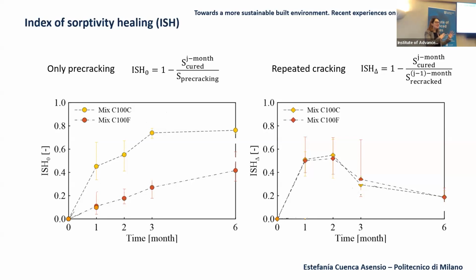This is in terms of sealing only at the surface, but what happens in the crack depth, regarding the inner part of the crack? Is it repaired or not? The structure is the same. On the left, we are analyzing only pre-cracking, not the recracking. On the right side, we have repeated cracking. In this case, we have calculated this kind of index using the sorptivity. Sorptivity is a rate of absorption, as I explained with the prismatic specimens and so on.